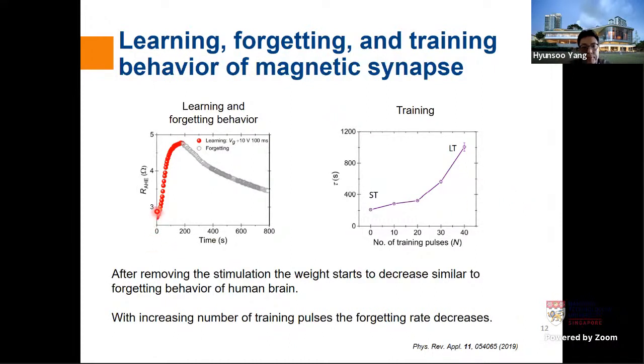We can program it by applying a certain positive voltage, for example. Then we just remove our input. Then what will happen? The signal can decay gradually over time. And then we measure those relaxation time constants, and then we plot those as a function of the training pulses. So depending on how many pulses we initially train, then let it relax, we find the time constant can change from 200 seconds to about 1,000 seconds. So we can easily manipulate those decaying, forgetting times.